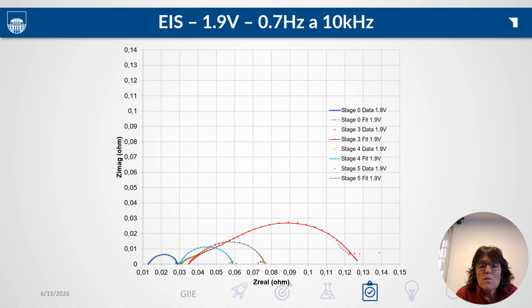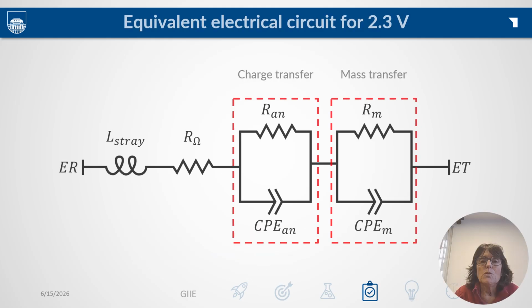This slide shows again how the 2 depressed semicircles grow markedly with degradation, and after regeneration the semicircles collapse back to almost the pristine stage, in agreement with the kinetic recovery of the catalyst. At 2.3 volts, the situation is different. Here we fit with a resistance-constant phase element branch to account for the mass transfer or diffusion process.